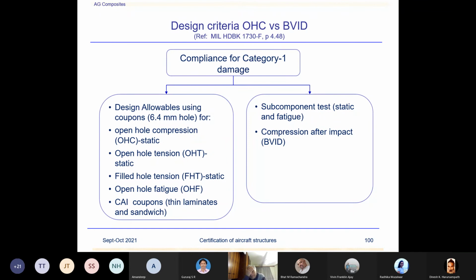Okay, now compliance for these damages. How do you satisfy the requirements? Usually, for the category 1 damage, you will recognize the undetectable damage. So in order to satisfy or meet the compliance for that damage, we normally would use a 1/4 inch hole or 6.4 millimeter hole for open hole compression, open hole tension, filled hole tension, and compression after impact for thin laminates and sandwich.